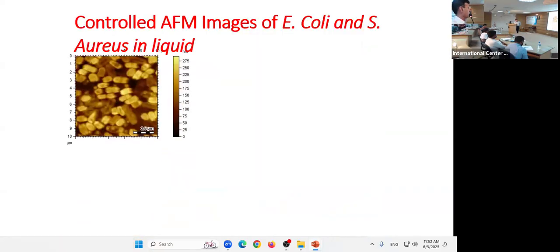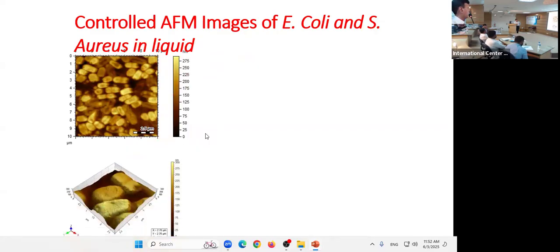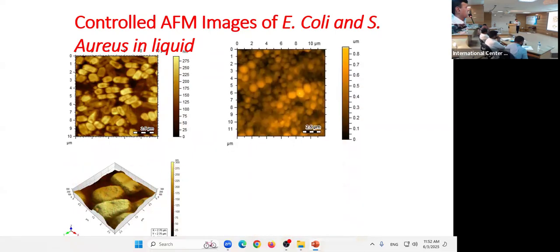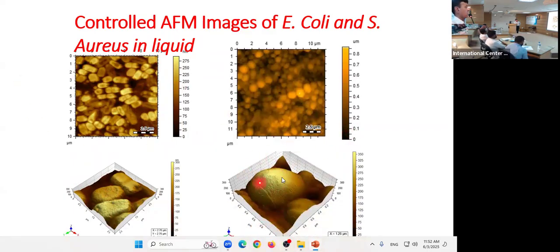This is what I mentioned earlier, that this is actually E. coli, a sample from the E. coli, and as you can see there are some grooves in the middle, like this one. These were the bacteria which were analyzed. This is the E. coli which we analyzed, and this is the Staph aureus, and you can see this is a single S. aureus, and on the surface there are particles and lines with extremely good resolution. In the past you could not image bacteria with such good resolution to see what is on the surface of the bacteria.